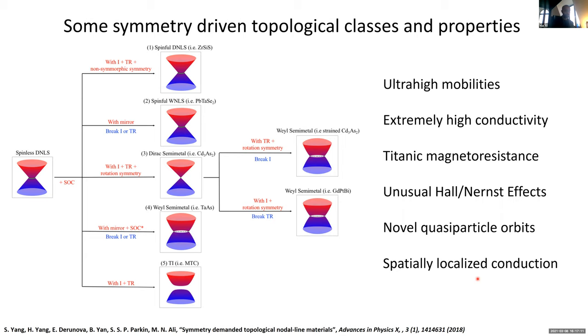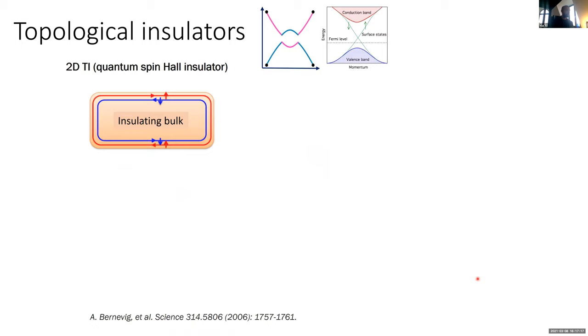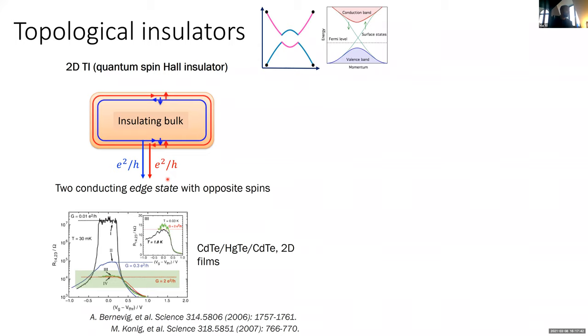To touch on those three classes very quickly, the topological insulators are where you have the band inversion, but at the boundary you have a connection between the conduction and valence bands via surface states or edge states or some kind of boundary localized state. In 2D, this was manifested as a quantum spin Hall insulator, which had a quantized conduction that was seen a long time ago now. I remember when this was relatively new, but I guess I'm getting old. It's been almost 15 years. So cadmium telluride, mercury telluride, this was seen in 2D.